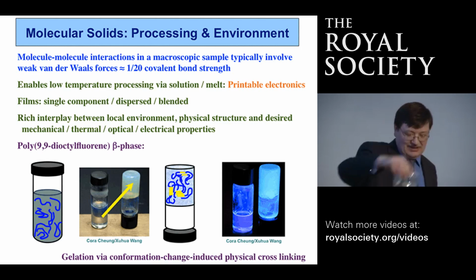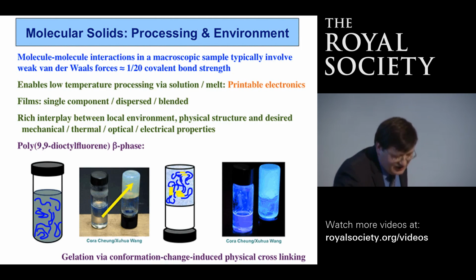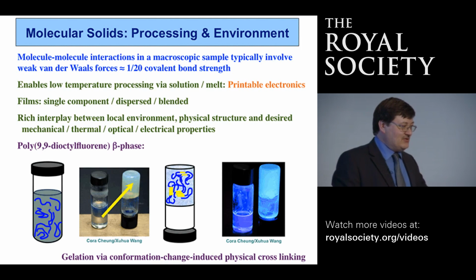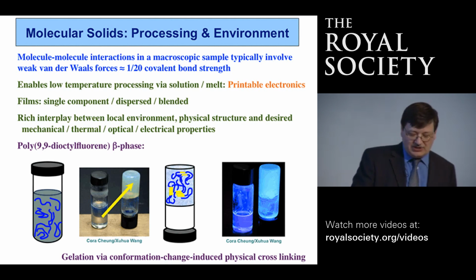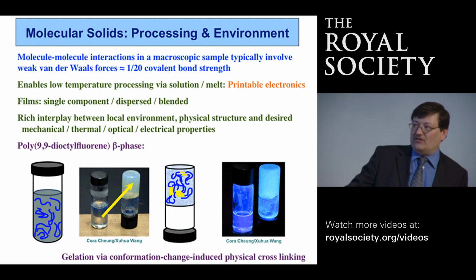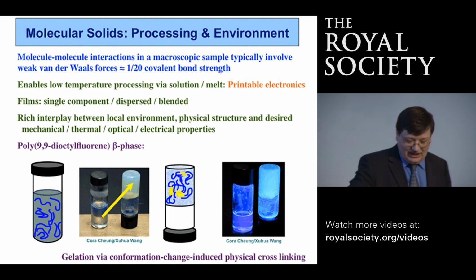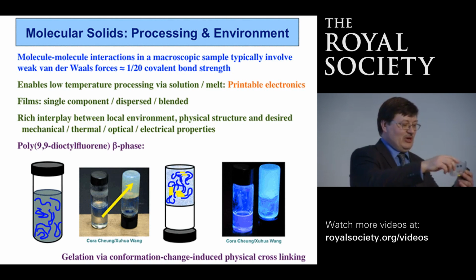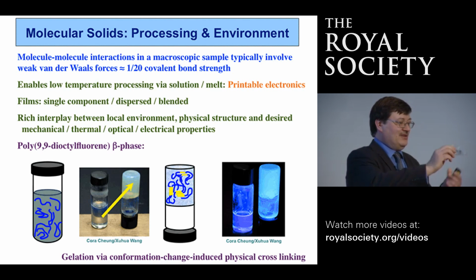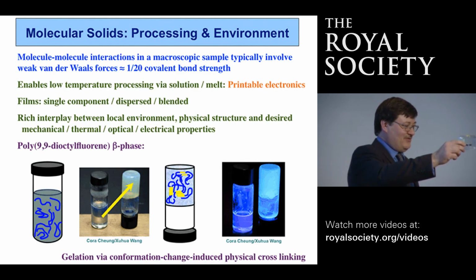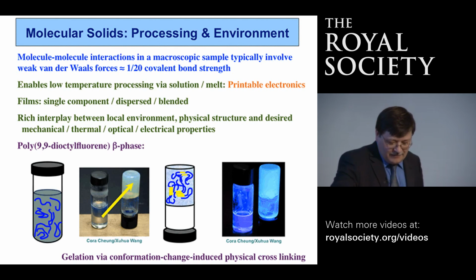We've got a solution. We can basically change the nature of the solvent that we use to dissolve the material, and we can use a less good solvent. And in the presence of this less good solvent, we end up with something which is called a gel. And so here's our gel. Basically, the gel is now a solid, and it doesn't fall down when you turn it over. The solution basically moves like a fluid. The gel basically stays put. And that's just a physical change.